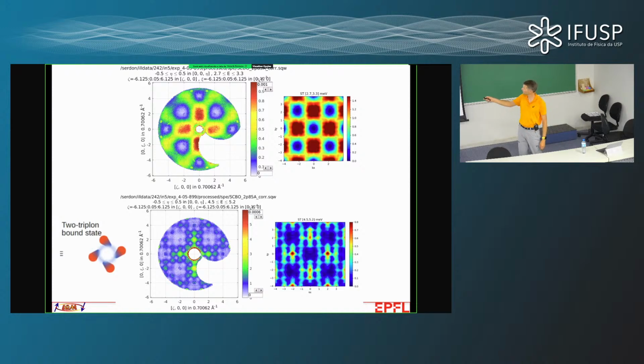Okay? At 0 pressure, this is the momentum distribution of intensity, so the structure factor of the single triplon excitation. This is a prediction from tensor network calculations. This is the 2-triplon bound state, and this is the calculation from tensor networks. And you can see it starts to look rather promising, so we're quite excited about this. But the data were taken this week, so I cannot tell you anything about how well it matches or not. You'll have to wait a little bit before we have analyzed it and are able to publish this.